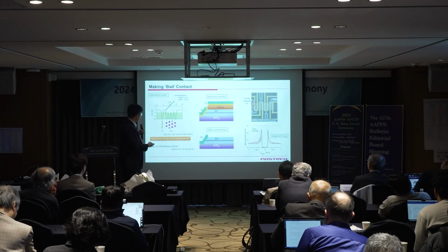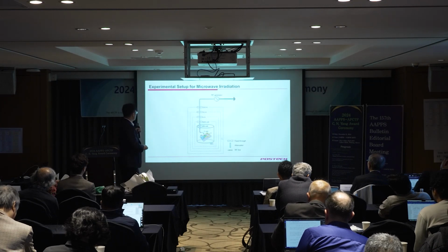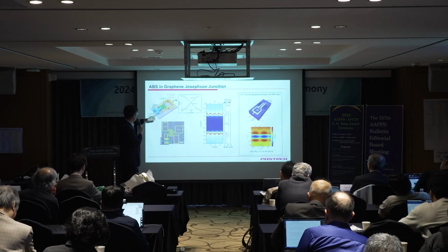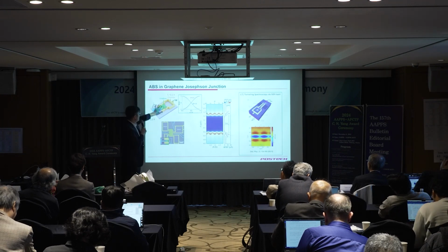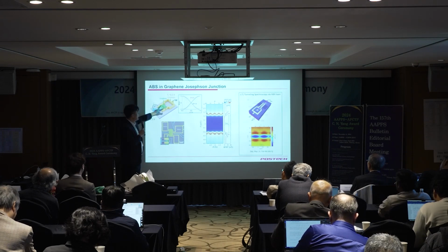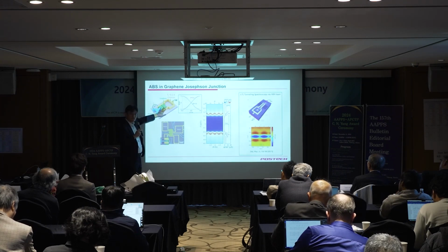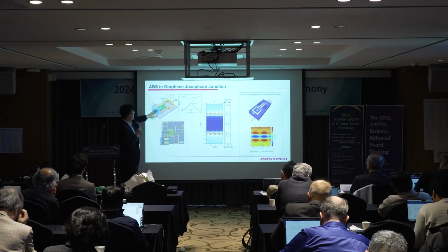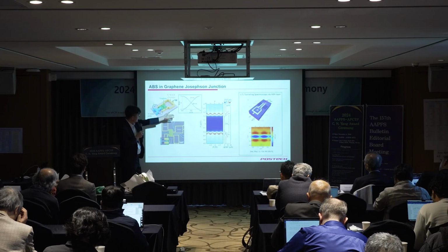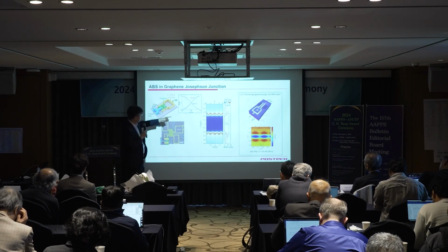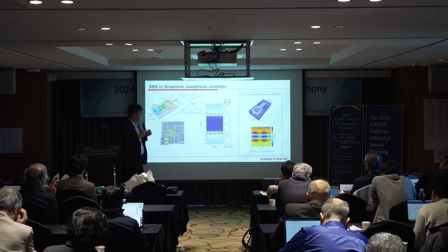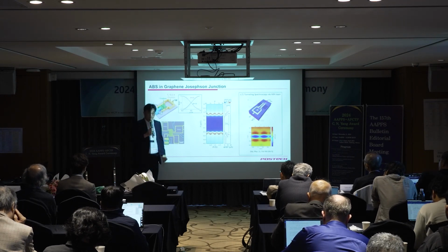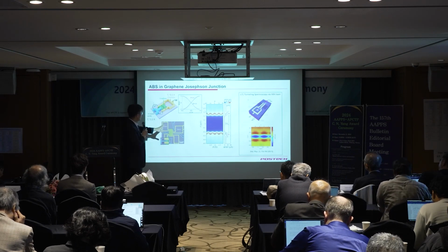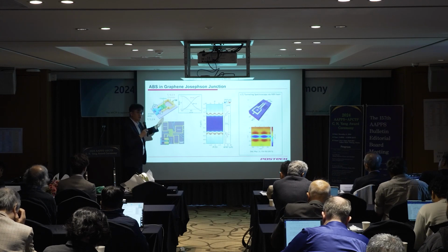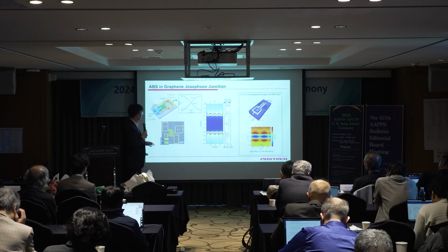So the device looks like this. Basically this is the schematic. This is the graphene, and we make a superconducting contact on these two sides, but we make it into a ring so that we can control the phase difference between these two superconductors by applying a magnetic field and form the Andreev bound state inside the graphene. We use the tunneling superconducting contact on the side of the graphene and measure the differential conductance as a function of voltage. That shows oscillatory behavior as a function of magnetic field. Basically, that shows the oscillation that I showed for the Andreev bound state. So this is one very cute idea, using a tunneling contact, but it's powerful.